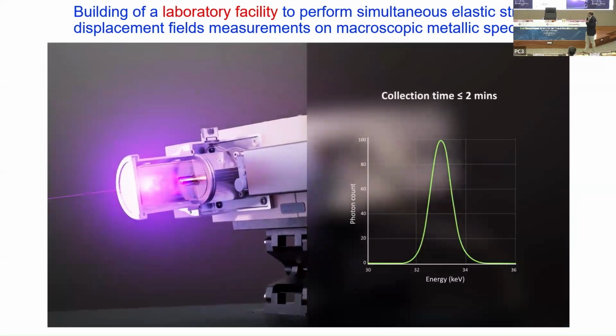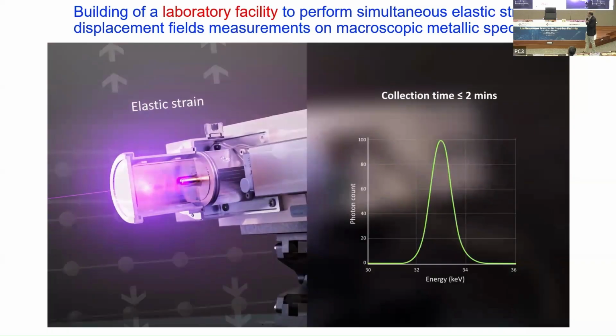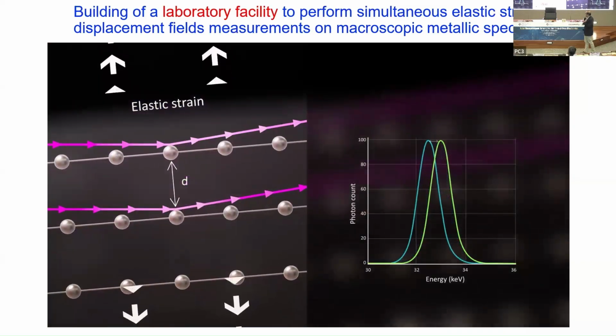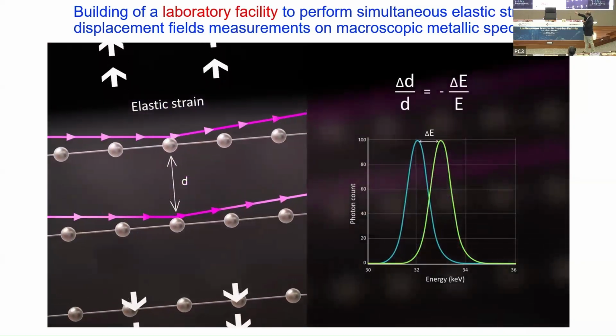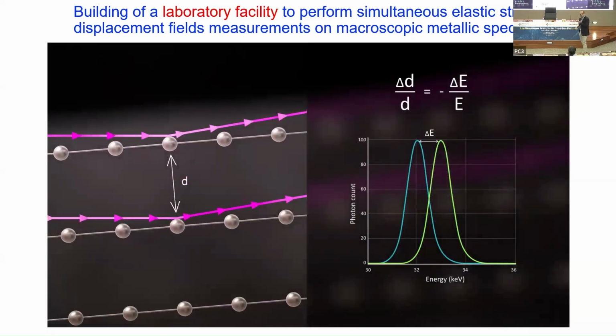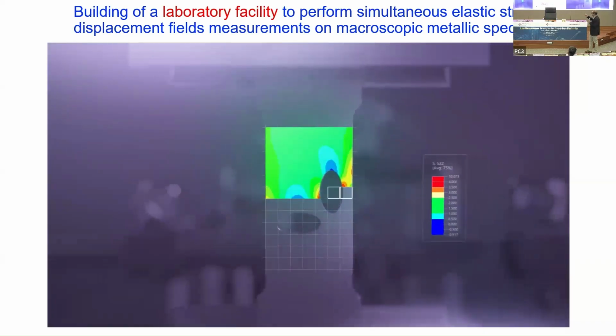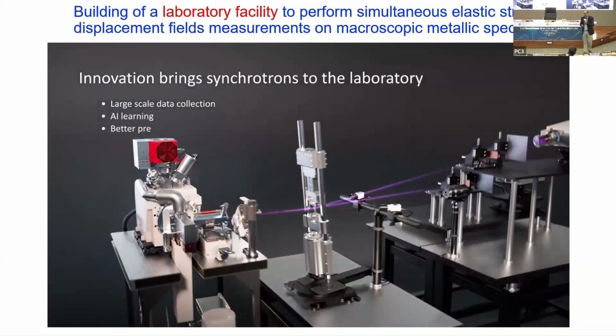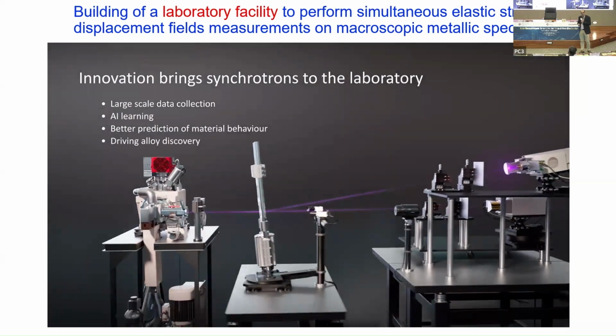And as you load this specimen, you have first this normal diffracted beam. As you load it, the spacing of the atoms changes, and the energy spectrum moves. And that is essentially how you can then get hold of the elastic strains. And then you can get effectively all this data throughout this specimen. So that's this idea about this facility.